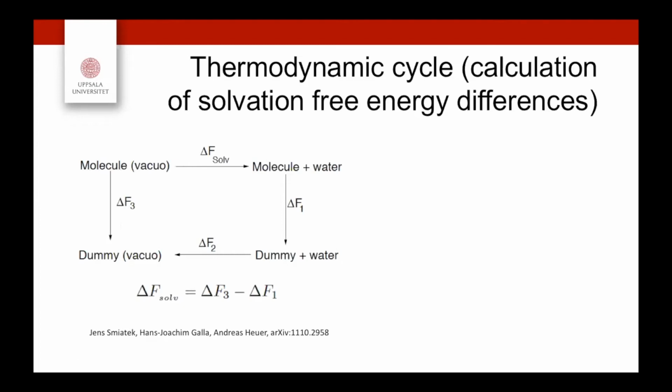So let's say we now introduce the molecule to the system with the water. The energy difference caused by such an insertion of the molecule should be equal to these three steps: the difference between introducing our molecule of interest to vacuum, then water to vacuum, and then from water in vacuum towards the system again where we have both water and molecule.